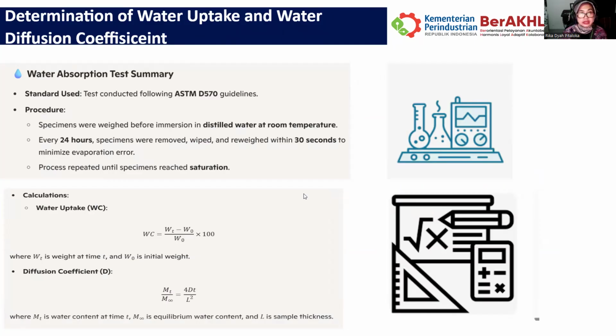Now we go into the determination of the water uptake and water diffusion coefficient. In summary, this is the water absorption test summary. The standard used is ASTM D570. The guideline shows the procedure: the specimens are weighed before immersion in distilled water at room temperature. Then every 24 hours, the specimen is removed, wiped, and reweighed within 30 seconds to minimize evaporation error. The process is repeated until the specimen reaches saturation.